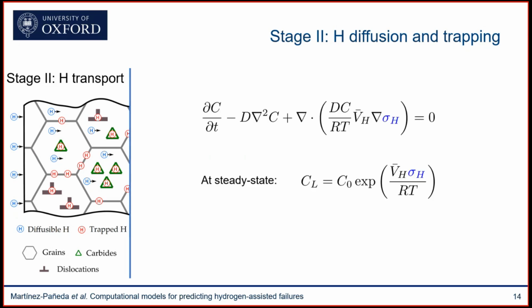And we know that, first of all, hydrogen transport is driven by gradients of hydrostatic stress and of concentration. So it's an extended version of Fick's law. And this coupling with mechanics is quite important. You can see here at the steady state, this is the hydrogen distribution within your material, within your component. And you can see that you have an exponential term that depends on the hydrostatic stress. So ahead of cracks and other stress concentrators, this term is going to be quite significant. So the coupling with mechanics is quite important.